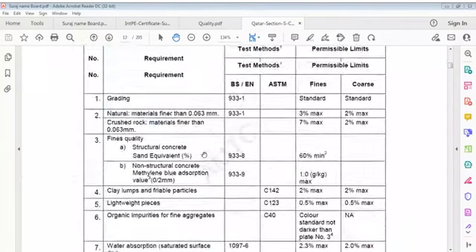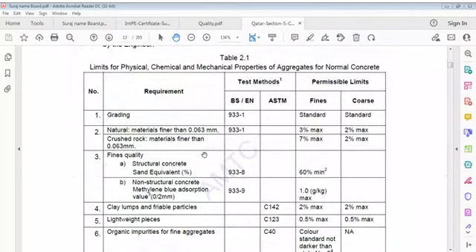In this, grading is number 1. BS 933-1. Here are the permissible limits, fines standard and coarse standard. We have natural materials, fine, and 0.063 mm. BS 933-1. The permissible limit for fines is 3% maximum, and 2% maximum for coarse. So it is that one.